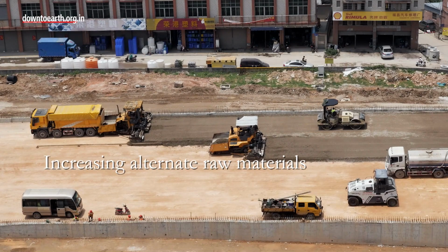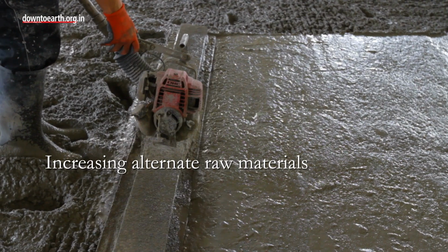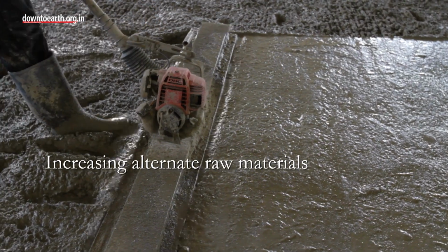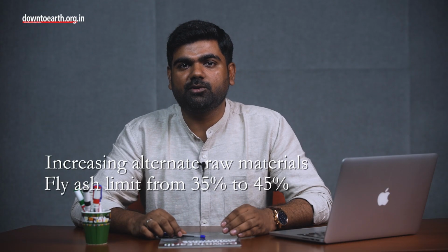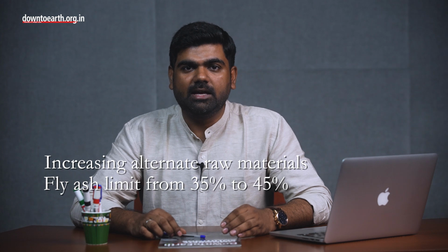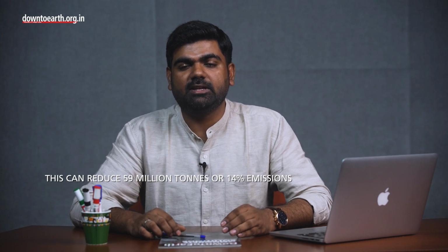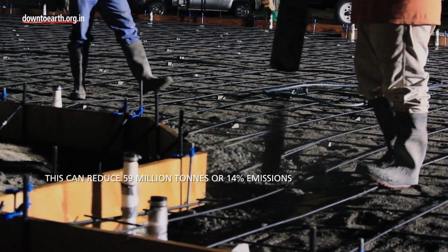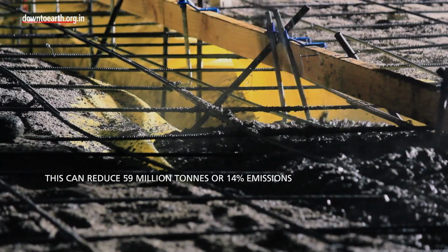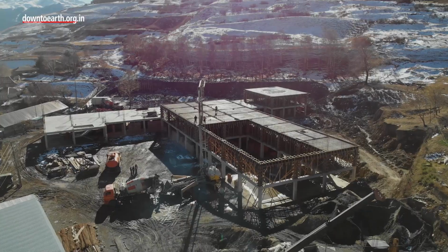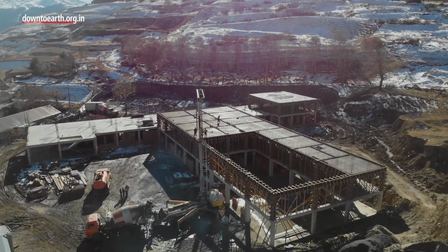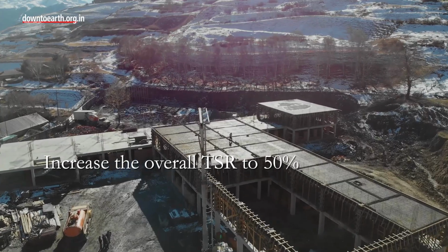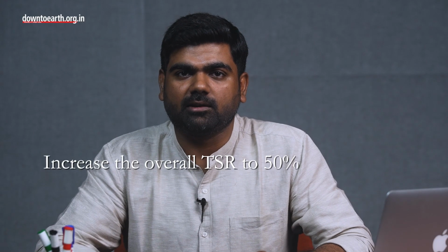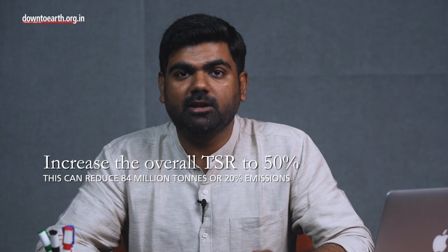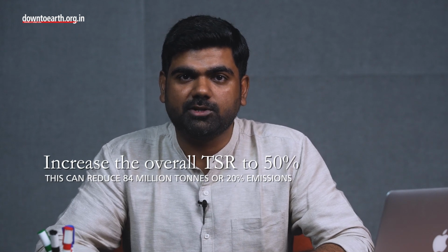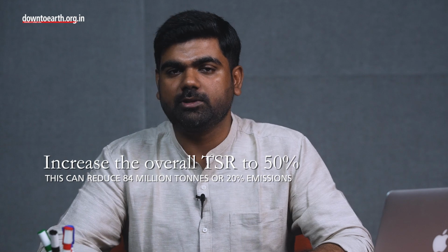Second is increasing the share of alternate raw materials like fly ash and slag in cement. The permissible limit of fly ash could be increased from 35 to 45%. CSE estimates this would reduce 59 million tons or 14% of the CO2 emissions as compared to the business as usual scenario. Third strategy is to increase the overall thermal substitution rate or TSR to 50%. This would reduce 84 million tons or 20% of the CO2 emissions as compared to the business as usual scenario.